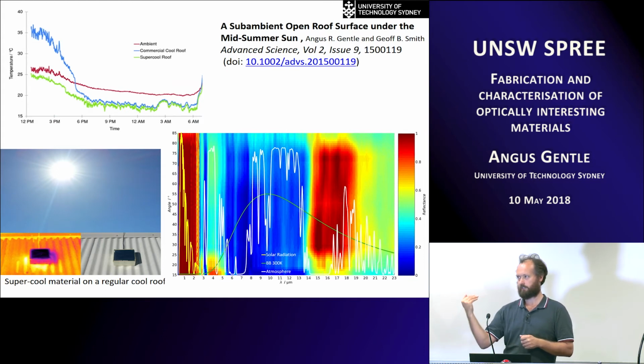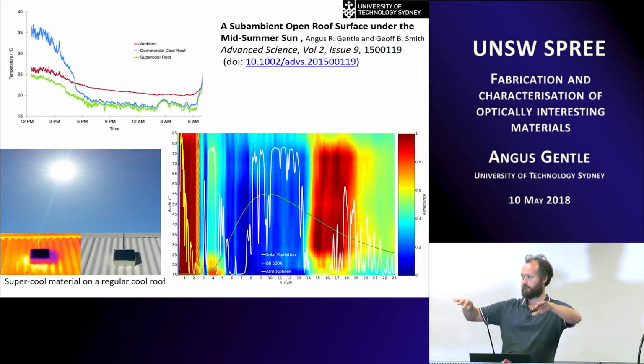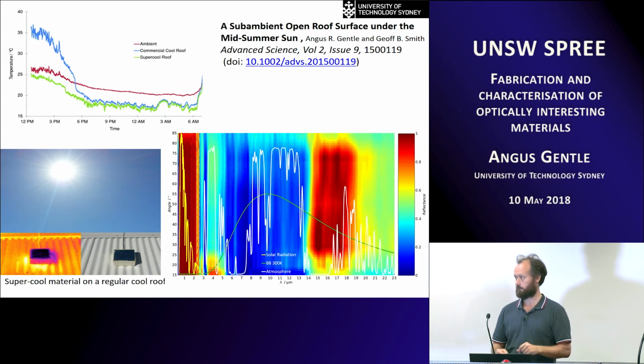So you can use it in back reflectors in phones. People have also used it for concentrating solar, because it reflects really strongly up to 1 micron. So you put that on as your mirrors, you can get the sunlight for the silicon cell, but not get the extra heat. So there's a couple of other things people used it for, and we went, that's cool, let's coat the back of it so we can actually get the solar reflectance in the near infrared up as well.